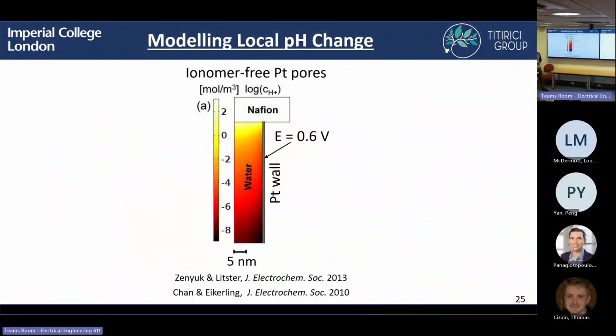And so we wanted to explore this local pH change. And this has actually already been considered in the literature by some groups around 10 years ago, where they look at, this is essentially modeling just a single pore in the catalyst layer, where you have your membrane. So Nafion is a membrane which transports your protons. So you're going from basically a very proton-rich concentration. And in their case, they modeled a platinum wall.